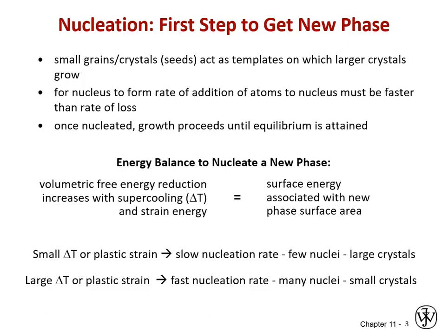Or if we're looking at an allotropic phase transformation, like our FCC iron to our BCC iron, we would look at how far below the equilibrium phase transformation temperature we were. If we were looking at recrystallization, we'd be looking at how much strain energy I put into that metal on my last cold working pass. So this, on the left-hand side of that balance, is our energetic drive based on a single or multiple state variables. And this will be per unit volume of material every time.